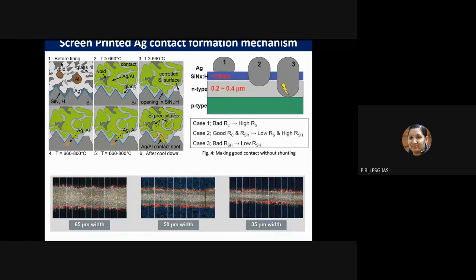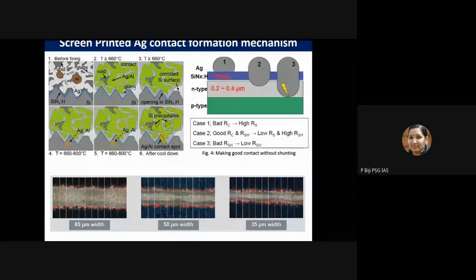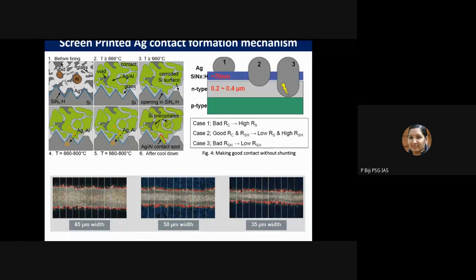The silicon nitride thickness is almost around 70 nanometer. It should etch out the silicon nitride to have a proper contact, but again it should not over-etch, because it will disrupt the overall process. So there could be some kind of optimal temperature for the sintering process.